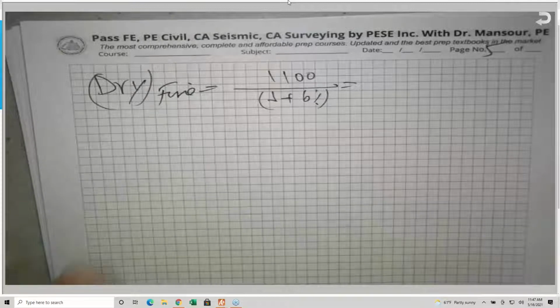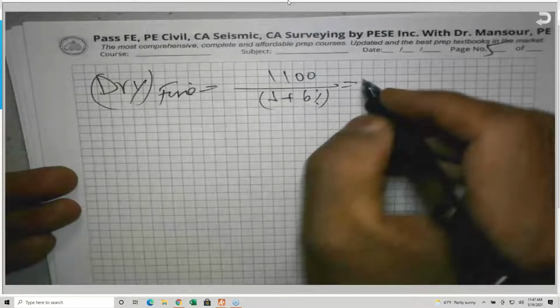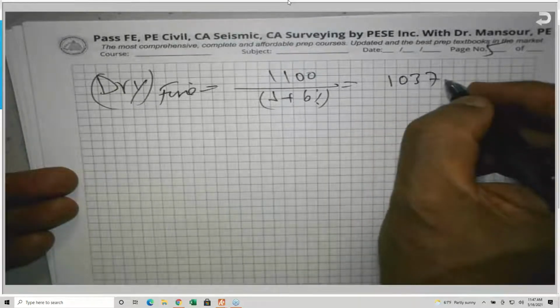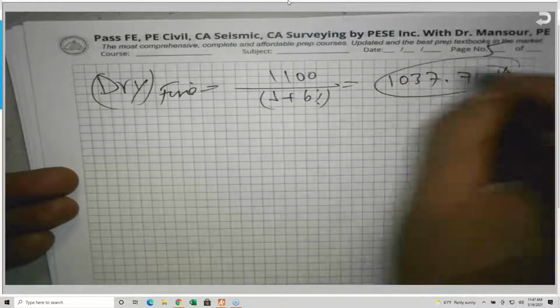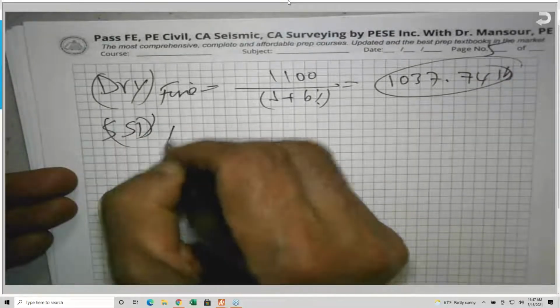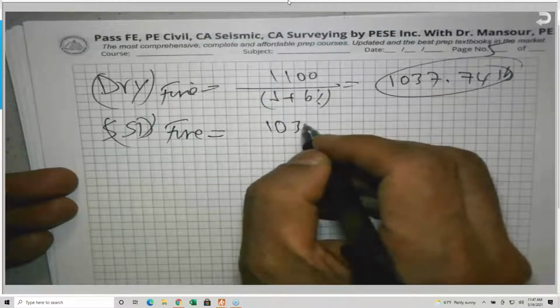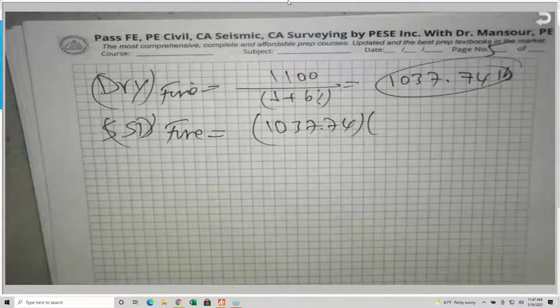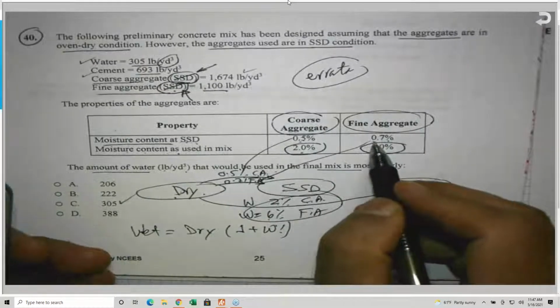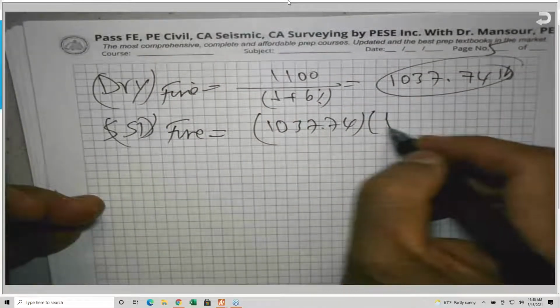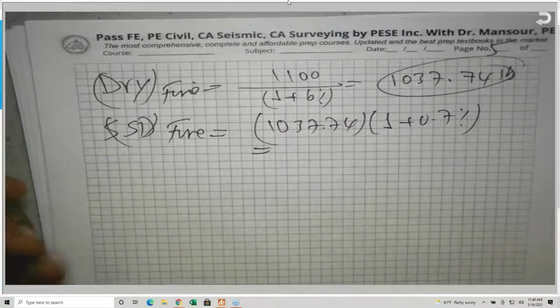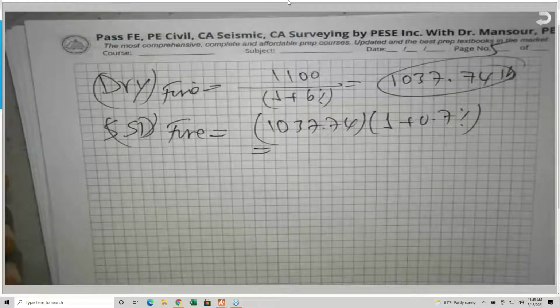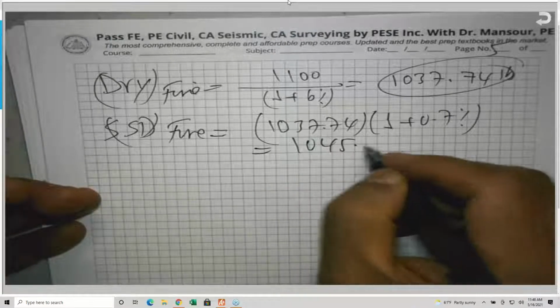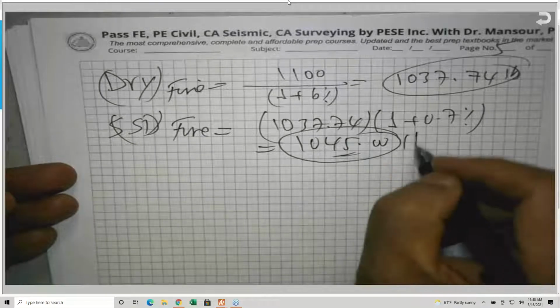So it is 1100 divided by 1.06 equal, it is 1037.74 pounds. The dry, I need to get the SSD for the fine, is equal to 1037.74. I'll multiply it by the percentage of the moisture to bring it to the SSD, which is 0.7%. So it is times 1 plus 0.7%. So this will give you times 1.007 equal. So this is 1045.00.